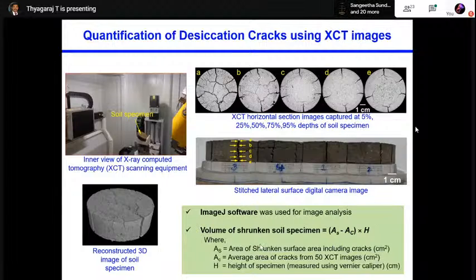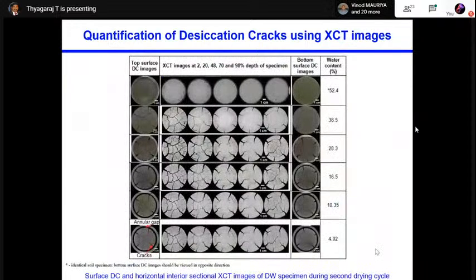So how we have calculated the volume of the sample, removing the crack area, is shown here, and we have used ImageJ software for doing it. This further shows very clearly, during the second drying cycle, the images which are captured at different depths. On both sides, the first column and the last column are the digital camera images, and in between are the XCT images. You can clearly see.